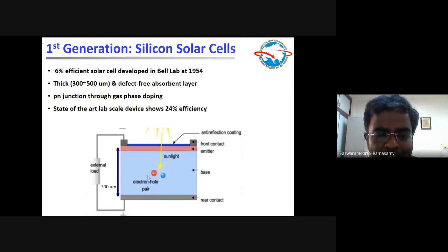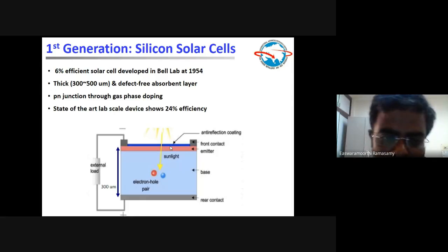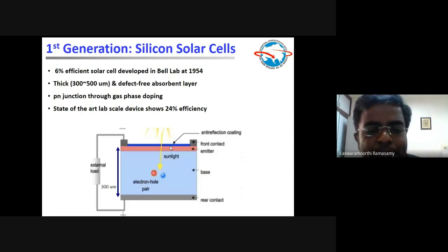Once the PN junction is there, you have to apply suitable contacts for electron and hole collection. The rear contact is aluminum in the silicon solar cell and the front side has silver grids. And you add an anti-reflective coating. This is a performance value addition, because some light was escaping from the device, so they made an anti-reflective coating. And then your cell is working.